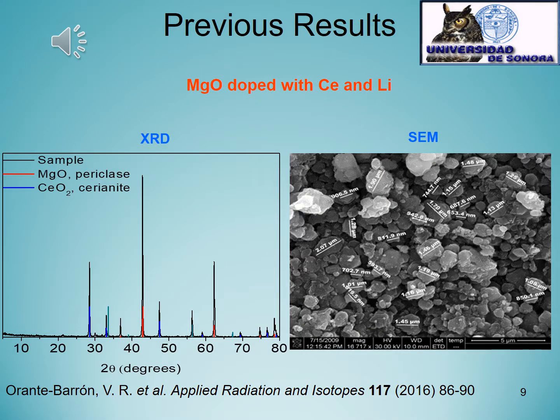In this respect, using glycine as fuel we obtained the following previous results. First, we could obtain magnesium oxide doped with cerium and lithium, the same as the one obtained with urea. In this case, we obtained a crystalline phase mixture of magnesium oxide and cerium oxide.